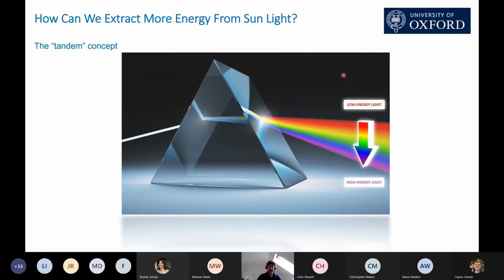But if we slice this spectrum up into two cells, so one cell absorbing the visible and one absorbing the infrared, that fundamental efficiency limit can be pushed up to 45%. If we go to 3 cells, it could be pushed up to over 50%, and so on and so forth as you get up to more and more junctions. Obviously, there's diminishing returns. Well, not obviously, but there are diminishing returns. And the fundamental limit is somewhere between 60 and 80% efficiency if we had an infinite junction solar cell where we're converting each section or band of the sunlight through a different solar converter.